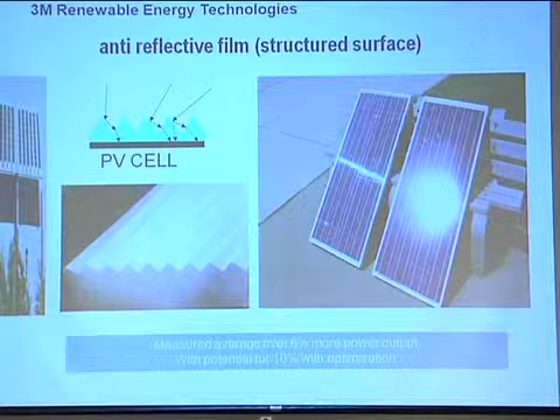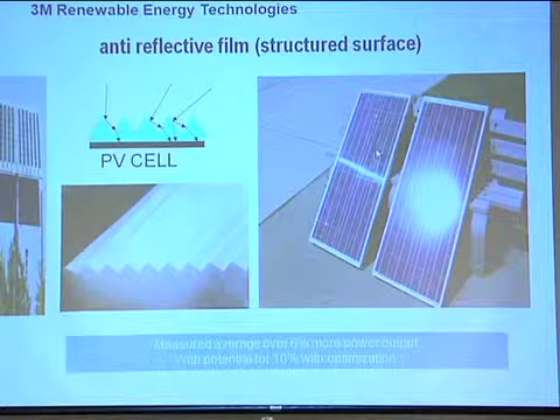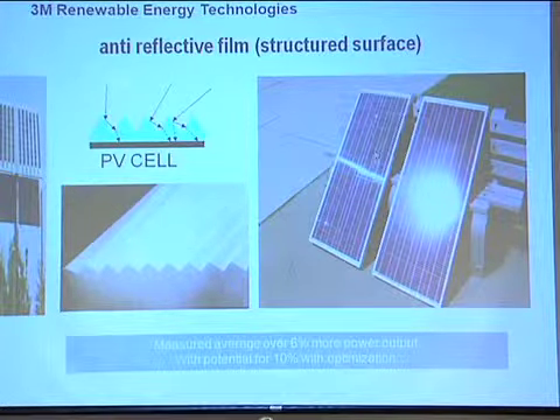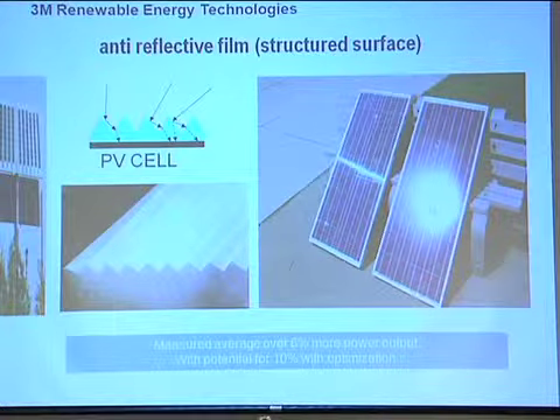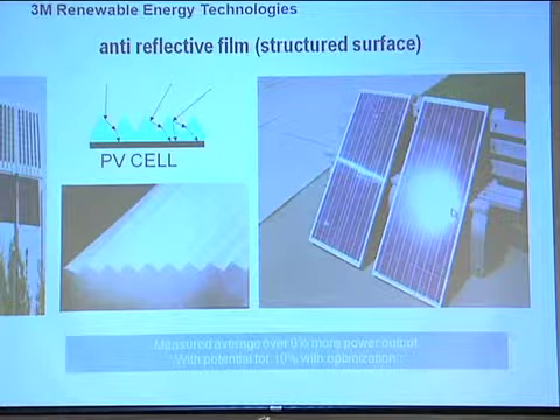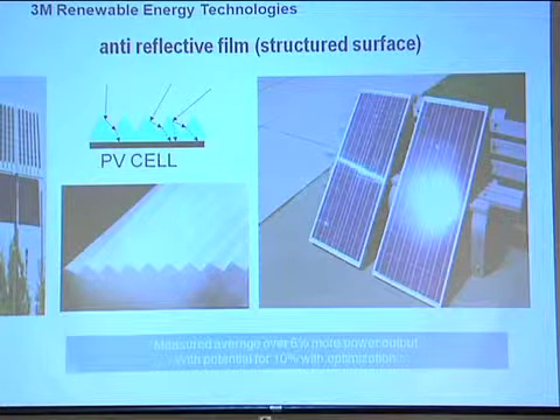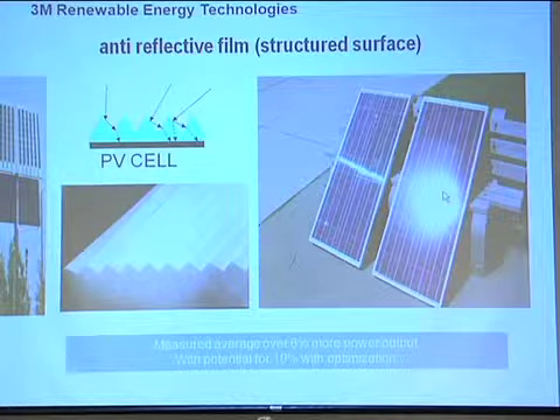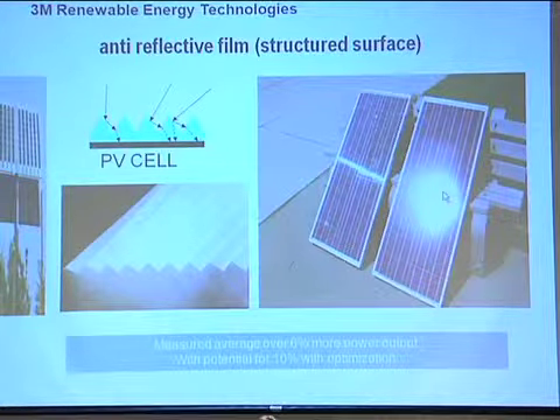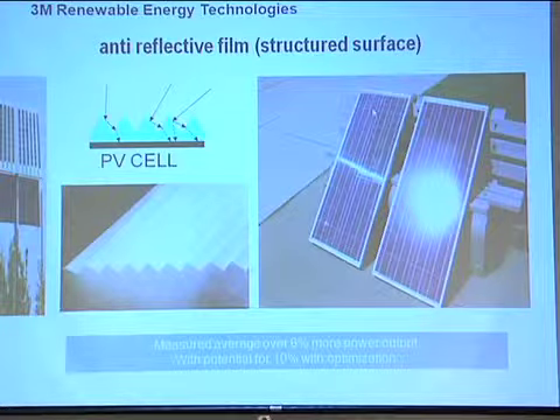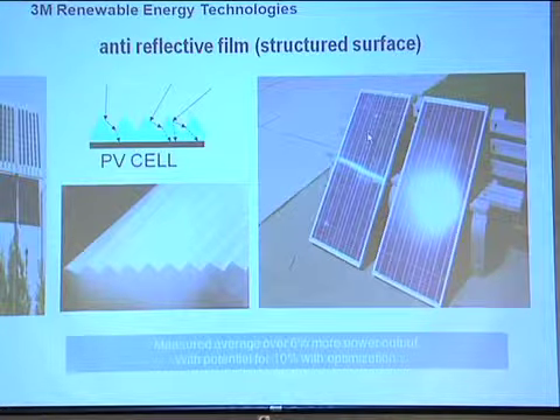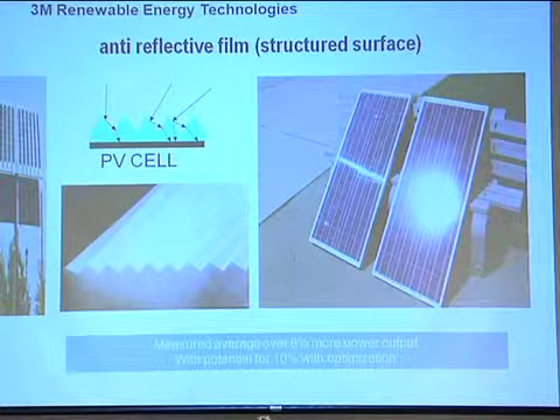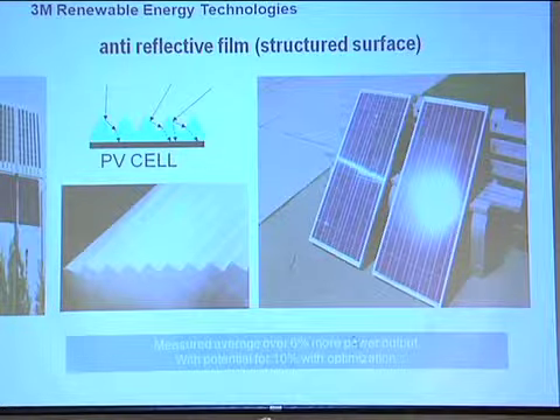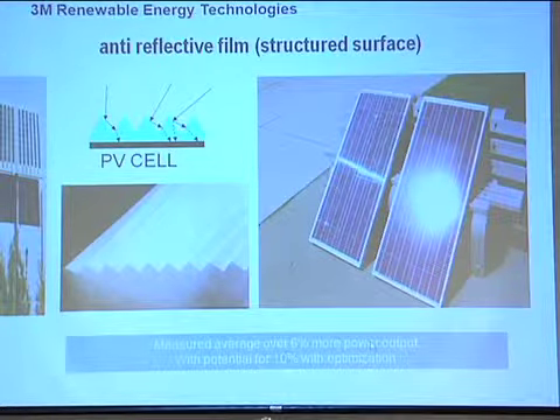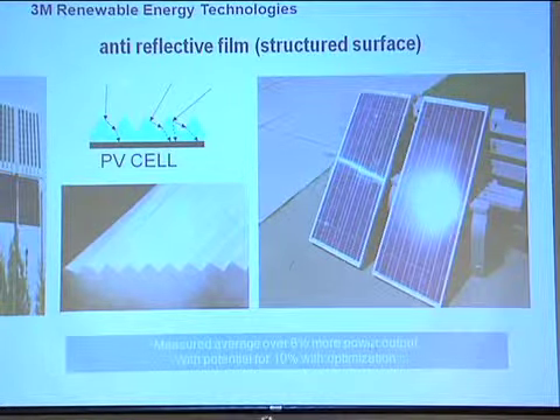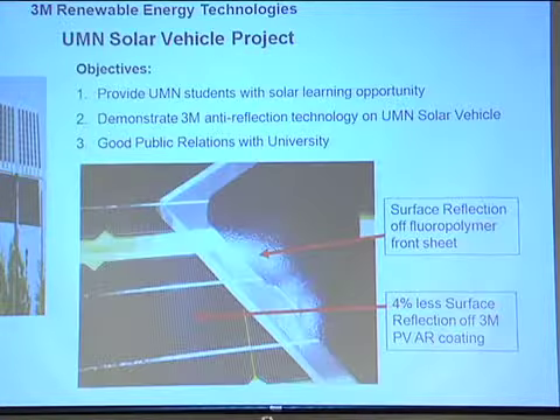And this shows a module with the structured surface film on the front of it. And you can see this one here has no surface structured film. You can see significant reflection of the sun's light. That's light that's lost. That's light that doesn't generate power. And here, 5% more light gets into the module, so you get 5%. We've measured 6 to 10% more light initially with certain designs under just the right conditions.